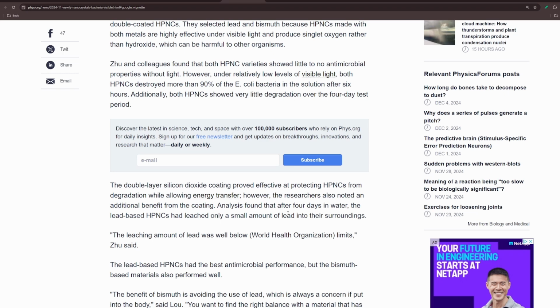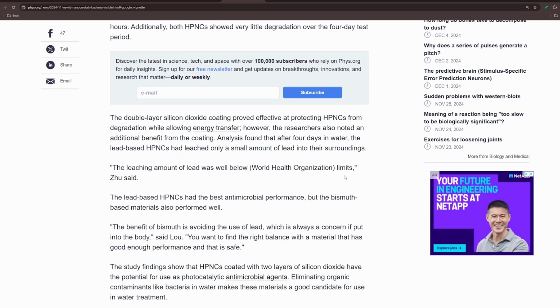Zhu and colleagues found that both HPNC varieties showed little to no antimicrobial properties without light. However, under relatively low levels of visible light, both HPNCs destroyed more than 90% of E. coli bacteria in the solution after 6 hours. Additionally, both HPNCs showed very little degradation over the 4-day period. The double-layer silicon dioxide coating proved effective at protecting HPNCs from degradation while allowing energy transfer.